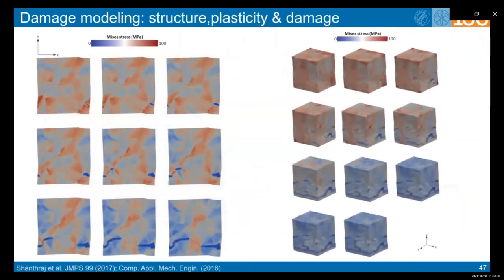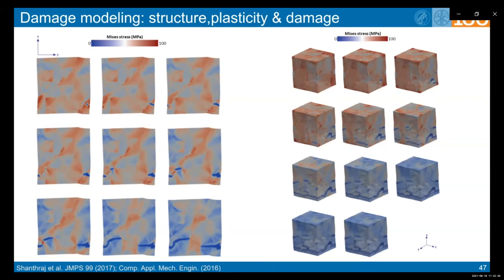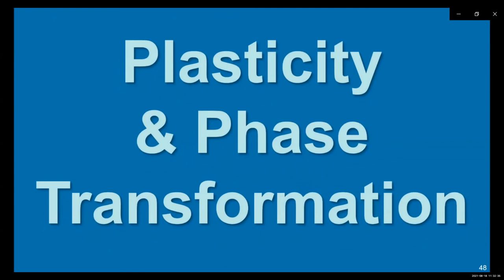Here is an example of how microstructure and damage can evolve during DAMASK simulations, reached in collaboration with Pratheek Shanthraj, now at the University of Manchester. A coupling between crystal plasticity and phase field simulations was developed, using the Allen-Cahn non-conserved variant of phase field theory. In the context of a generalized Griffith criterion, the integration point locally decides in a total energy balance whether to release energy as elastic, plastic, or damage energy. This is now being implemented into DAMASK to allow the microstructure to locally develop damage initiation features, calculable also in three dimensions.